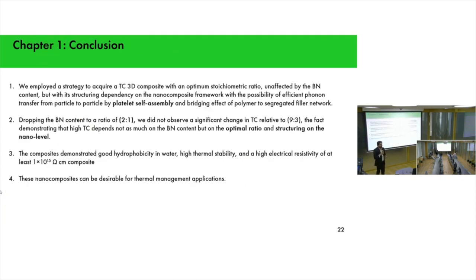So here we can conclude that we acquired a strategy for a 3D composite system with different ratios. We concluded that the increase in thermal conductivity does not only depend on the quantity of BN, but also on particle transfer by self-assembly and the bridging effect of the polymer in the segregated filler network. Dropping the content to a ratio of 2 to 1, we did not observe a significant change in thermal conductivity relative to 9 to 3, which shows that the optimal ratio and structuring at the nano level is more important. Our system is a composite with good hydrophobicity in water, thermal stability, and high electrical insulation, so it can be good for thermal management applications.